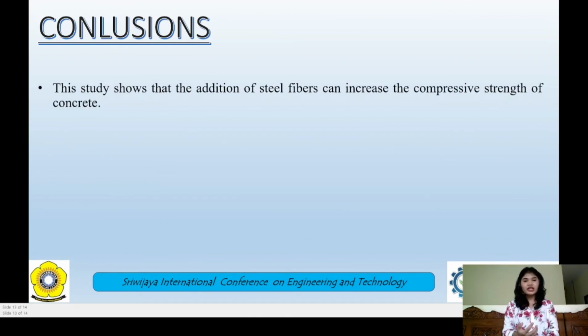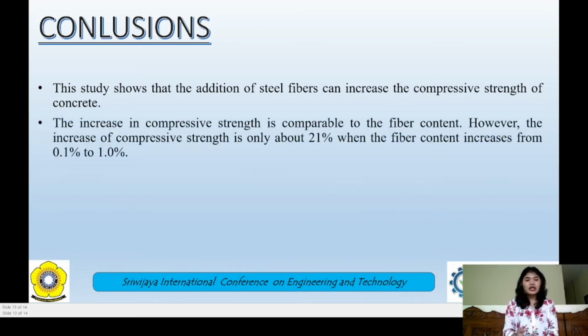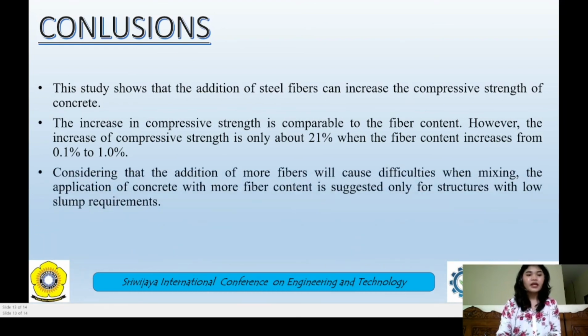The last point, conclusion. This study shows that the addition of steel fibers can increase the compressive strength of concrete. The increase in compressive strength is proportional to the fiber content. However, the increase of compressive strength is only about 21% when the fiber content increased from 0.1% up to 1%. Considering that the addition of more fibers will cause difficulties when mixing, the application of concrete with more fiber content is suggested only for structures with low slump requirement.